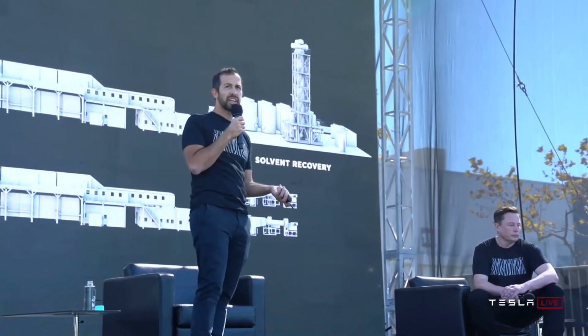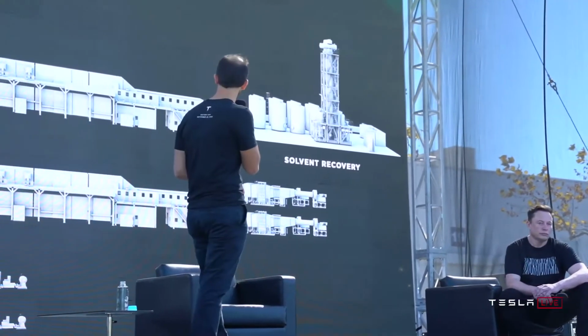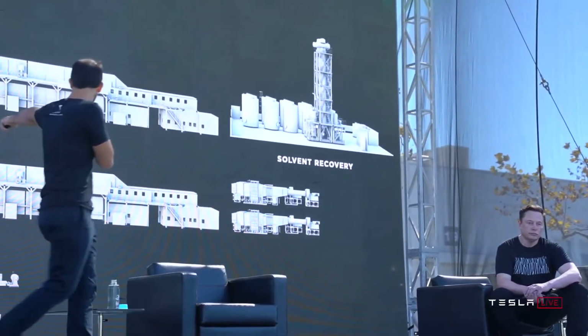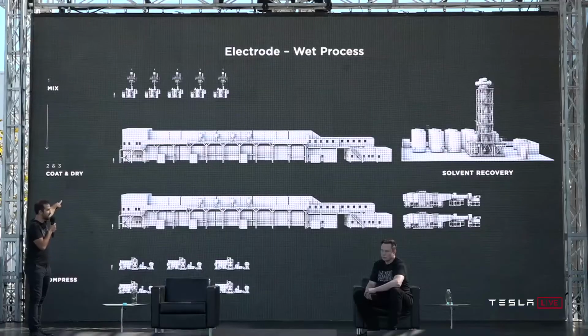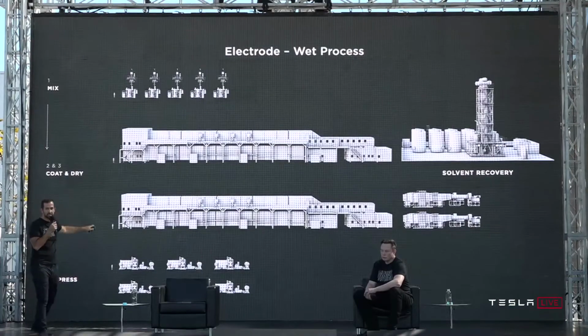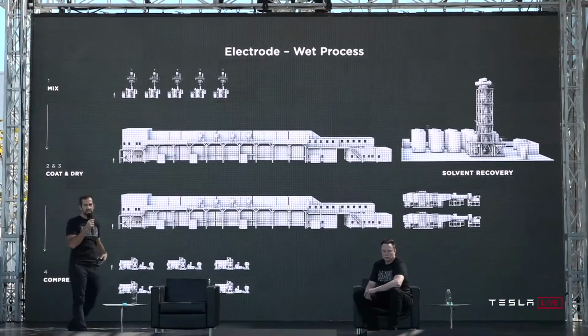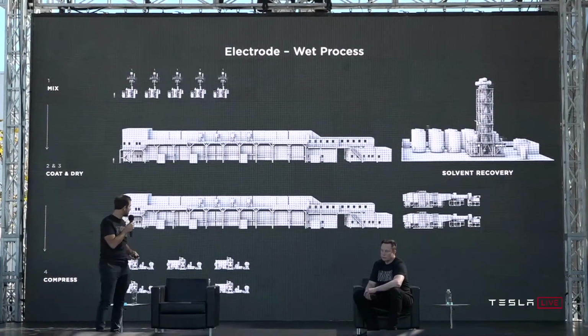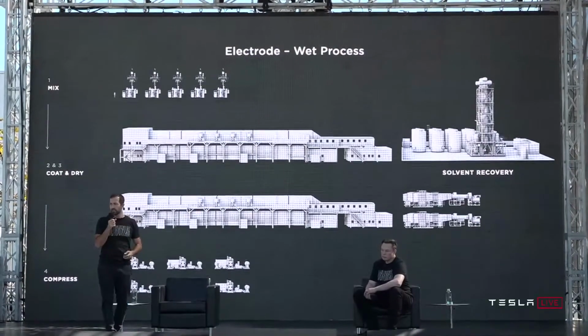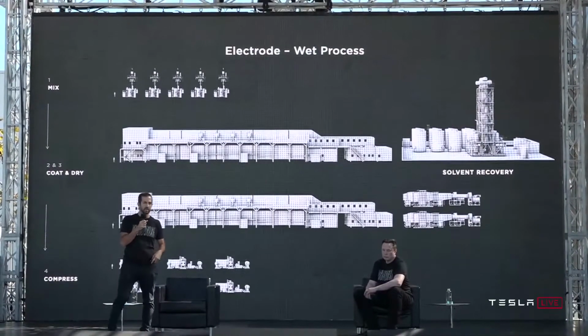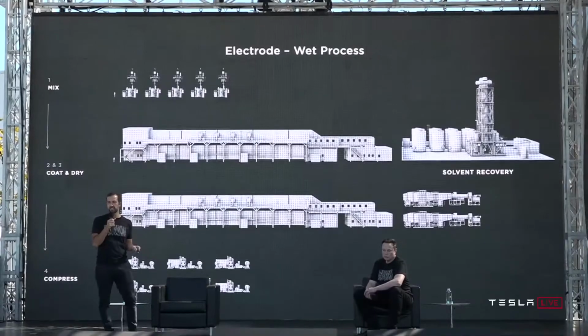When you're looking at this, you're like, wow, that's a lot of equipment for one step, especially when you consider that little speck next to the coating oven is a person. This is serious iron involved in making batteries. Wouldn't it be great if we could skip that solvent step, which is one of those dig a ditch and then fill it kind of things where you put the solvent in and then take it out and recycle it, and just go straight to dry mix to coat? And that's what the dry process really is about.